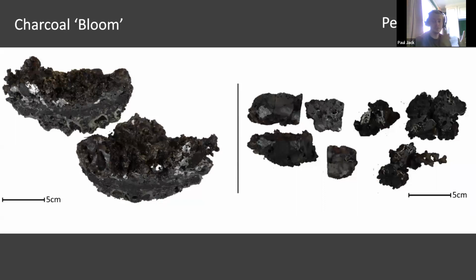Now, if we were to look at the blooms, I put them in quotation marks because in theory you should really be smelting for a lot more than 4 hours. But this gives us a really good idea of what's going on within the furnace. We can see on the left sort of homogeneous silvery masses within a much larger slaggy lump, effectively. And so what that's telling us is that we produced a decent amount of iron. If we continued things as they were, we'd probably have just a fair bit of iron.